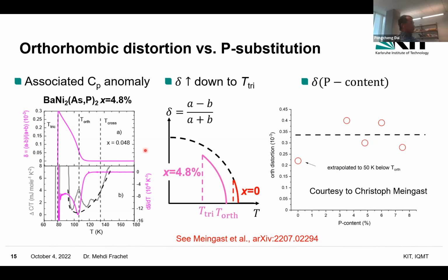So let me ask you a question. In the case of barium 122, you see this orthorhombic distortion sort of has the Curie-Weiss temperature dependence, right? Here, what you found is that it really seems like a truly second-order phase transition, right? Because in the case of barium 122, you have this structural distortion above the structural transition, like Junhao has seen clearly, the transport measurement shows clearly Curie-Weiss temperature dependence, and you guys see the same thing. But here, it's like you say, the heat capacity as well shows really, it's actually a phase transition. So you cannot say this is a fluctuation regime, right? I don't think we can say so. Yeah, I will show you the elastoresistance that we get in this undoped compound also. You will see it's also quite sharp.